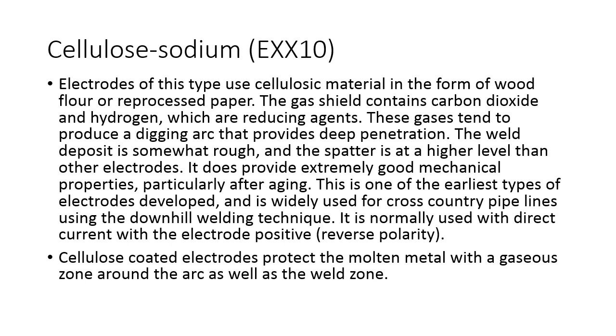filler metal types like the E7018. And you're also not going to have as thick a slag layer with E6010 because it doesn't have nearly the minerals in it that 7018 is going to have. So you're going to notice a difference in the way that it runs, and you're going to have a lot more spatter and fire. When you're welding with 7018, it doesn't produce the gas that this does to protect the weld zone. It's just got a really heavy slag formation that protects the weld pool from atmospheric contaminants.